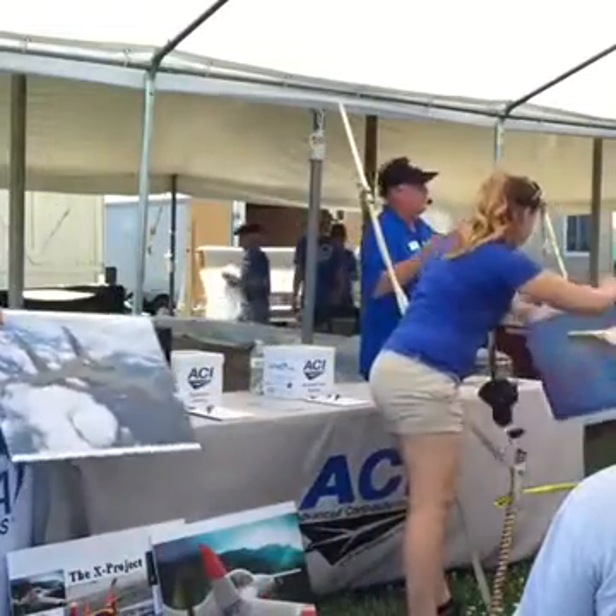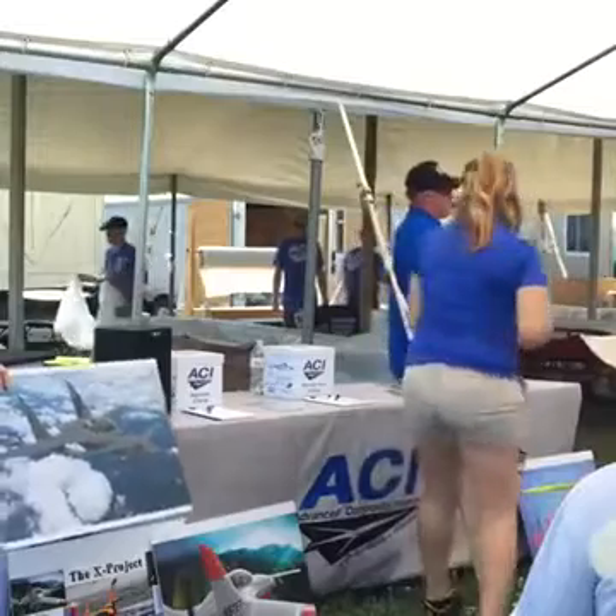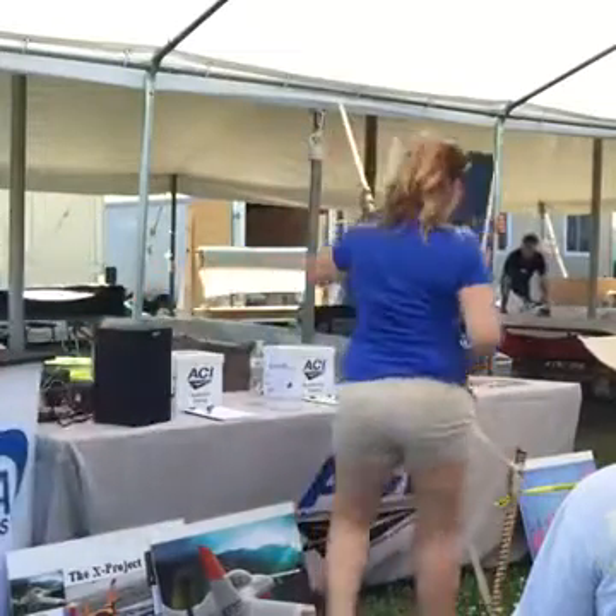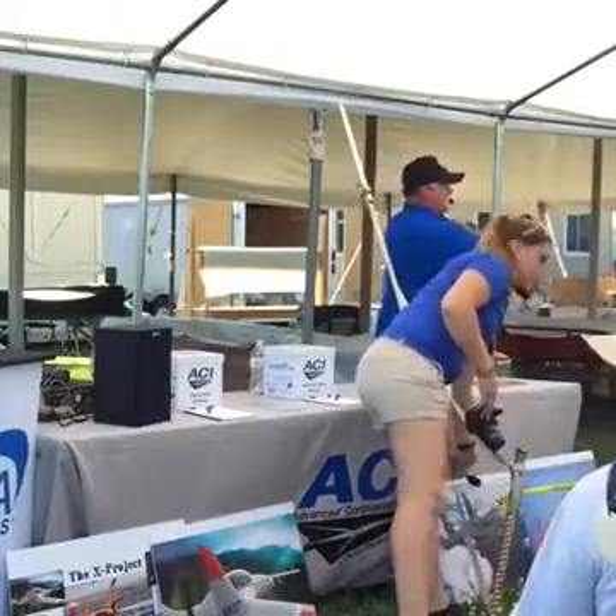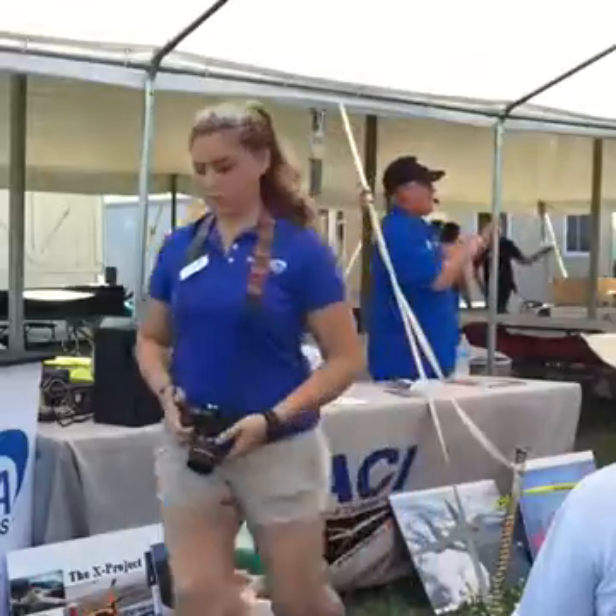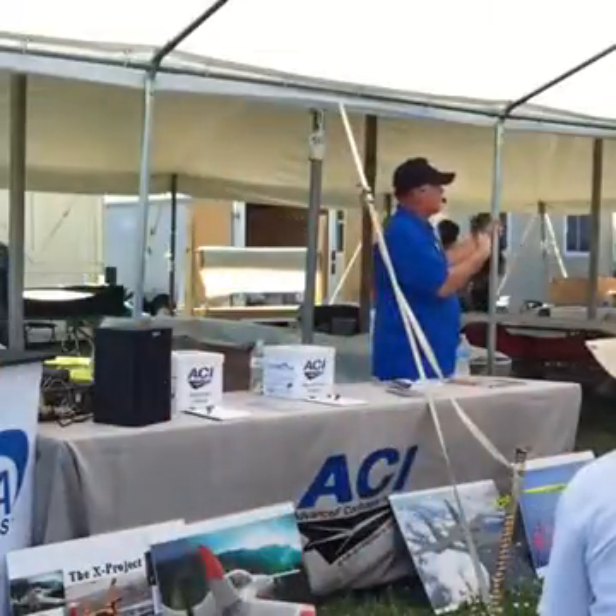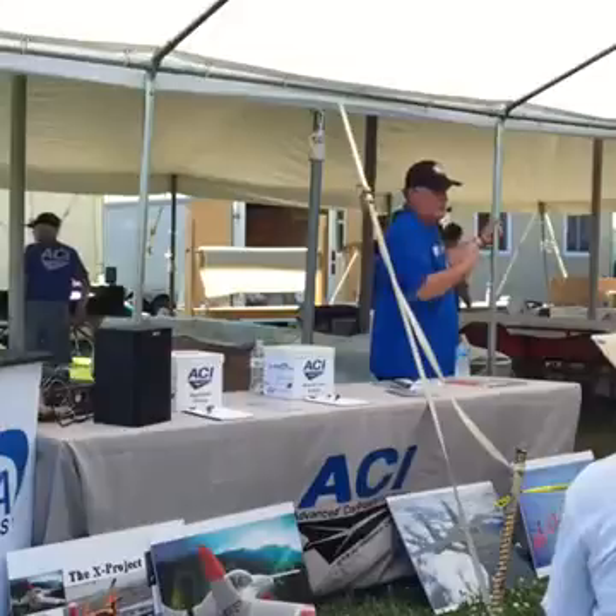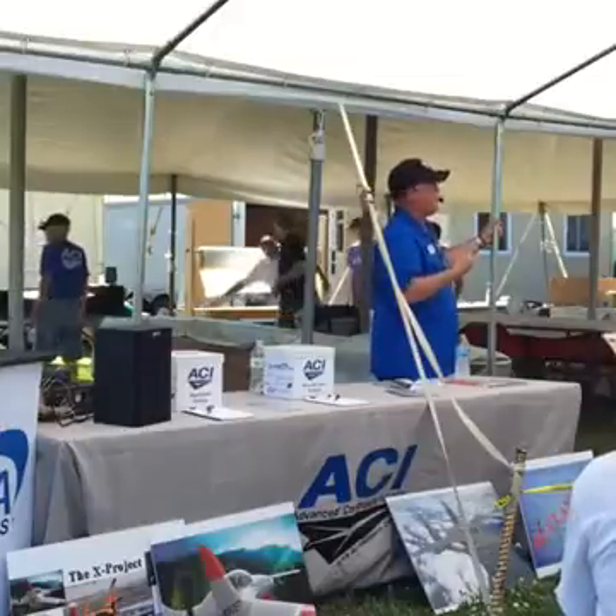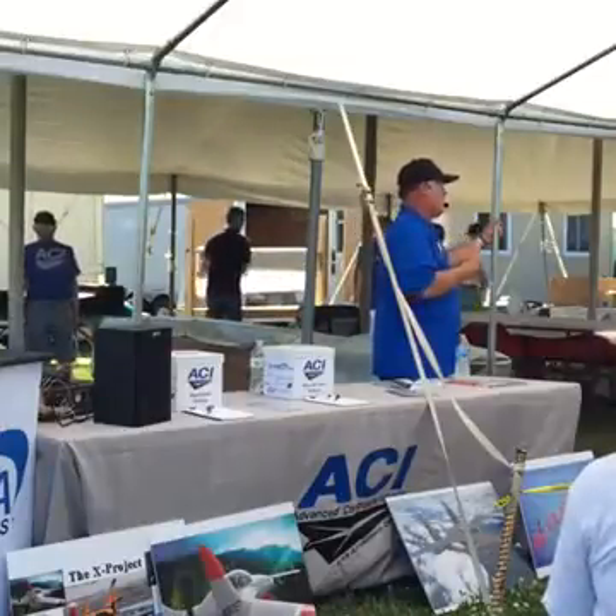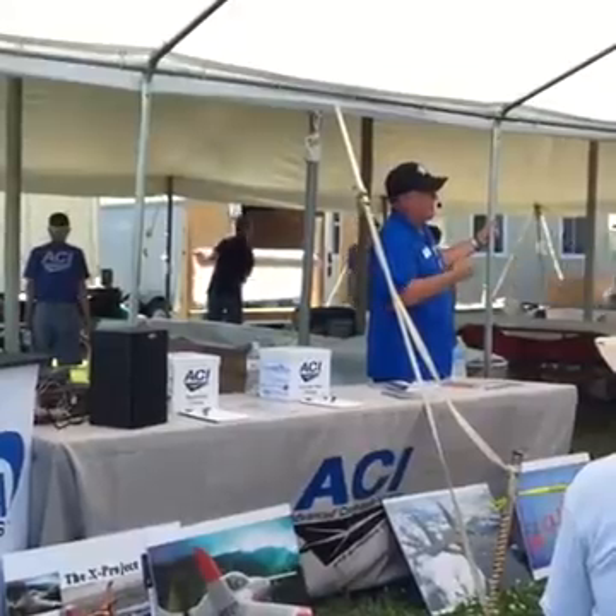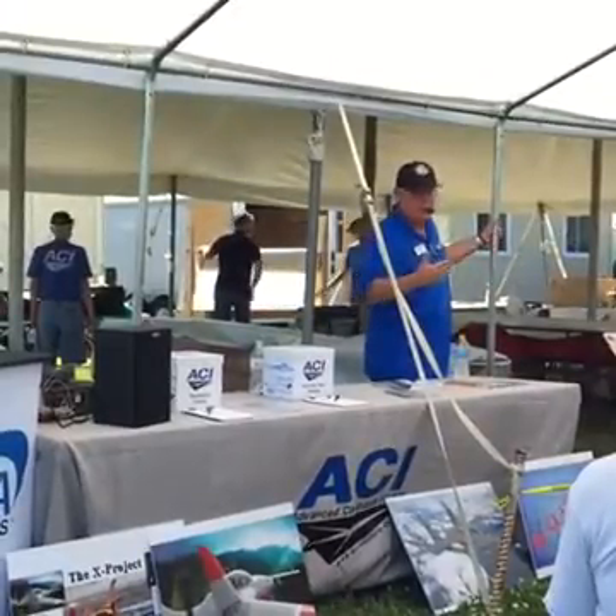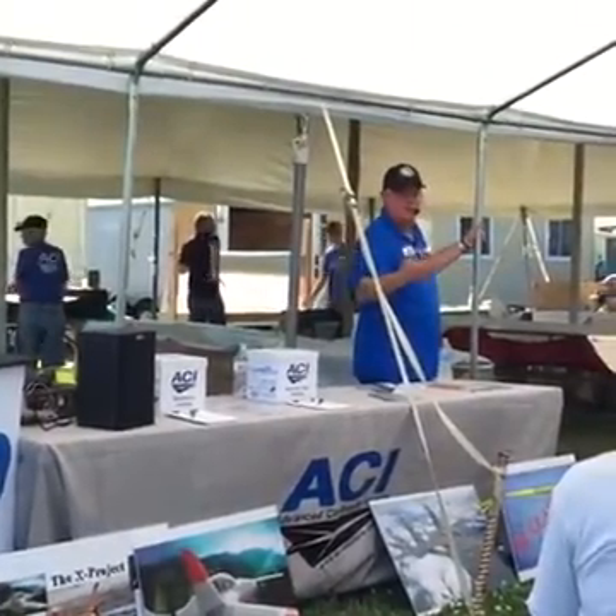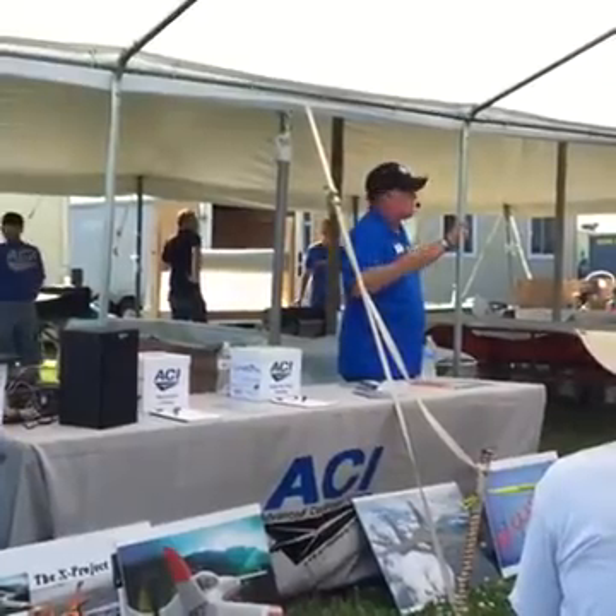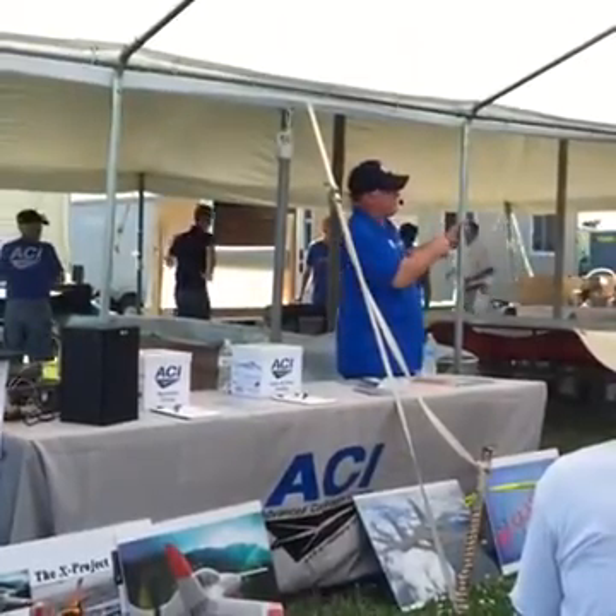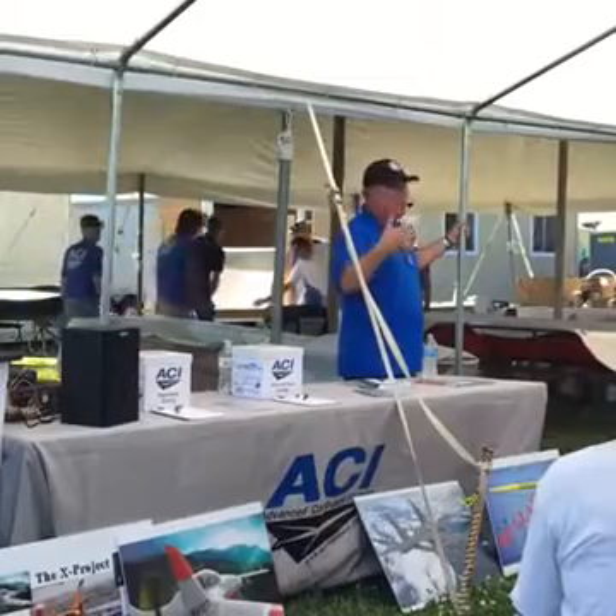It works very differently. So if we weren't using Innegra in these 2 layups, we would not have the glass that you see us putting down now. The reason the glass is there is for no other purpose than to control the encapsulation of the Innegra fiber that's going to be used close to the surface. It's also going to allow me to abrade that surface for primer later without getting into the Innegra and damaging those fibers. So I'll try to protect the critical laminate stack from any abrading in the future.